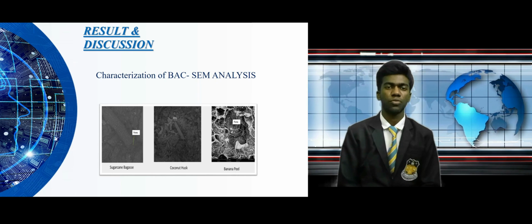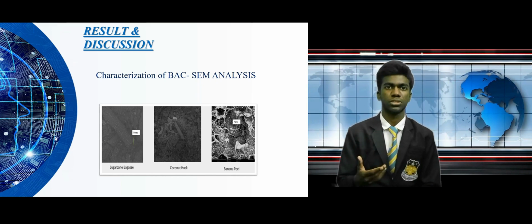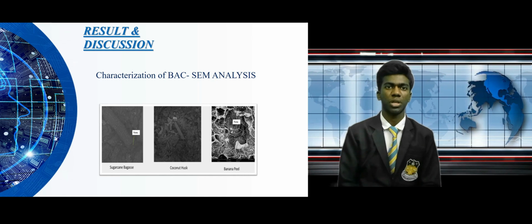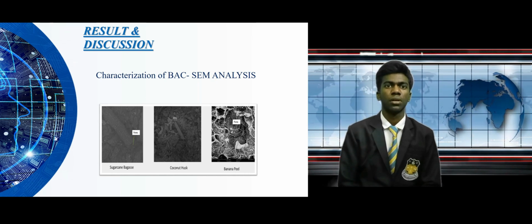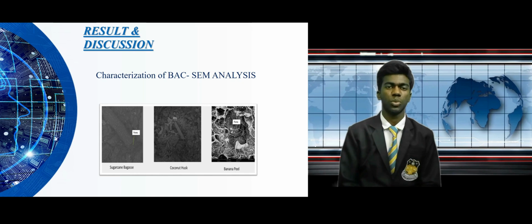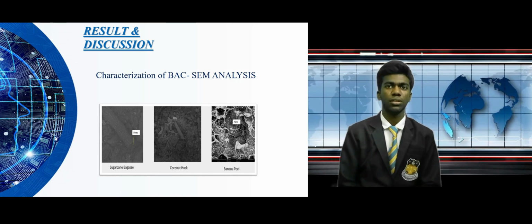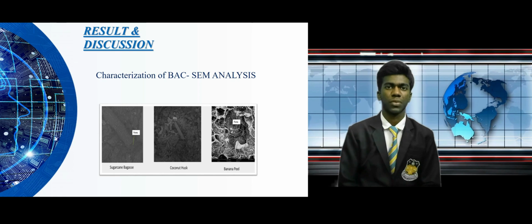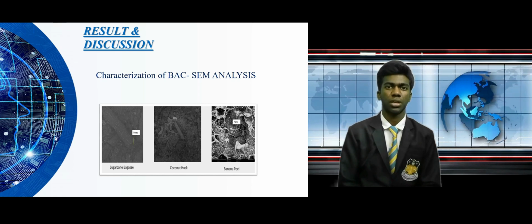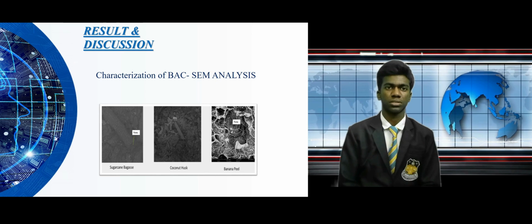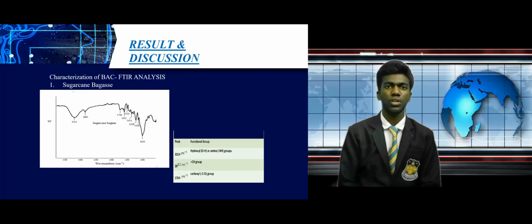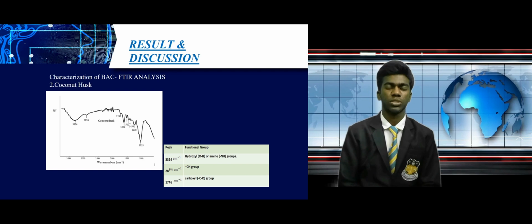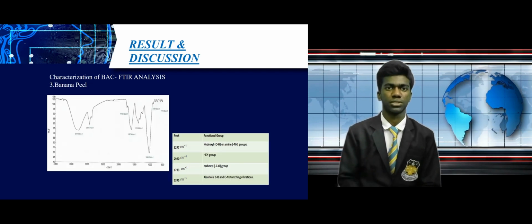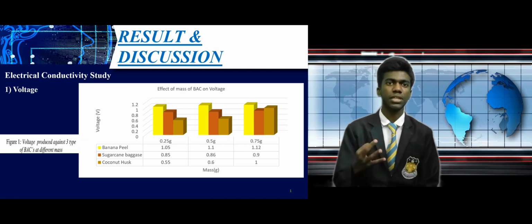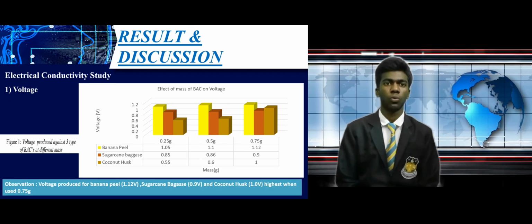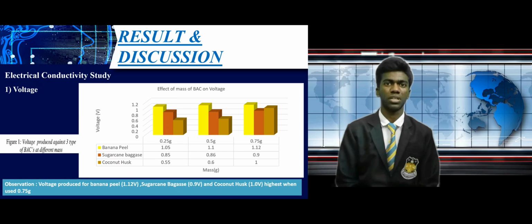In our research, we have done 5 studies which are characterization study, electrical conductivity study, lifetime and acidity level of BAC biobattery. Characterization study is done using SEM EDX and FTIR analysis. Here is the result of SEM EDX. Based on this, we find that banana peel has the most porous structure compared to coconut husk and sugarcane bagasse. In FTIR analysis, we found that banana peel has more functional groups than sugarcane bagasse and coconut husk. We have also done 3 types of electrical conductivity tests, which are voltage, current and polarization and power density curve.